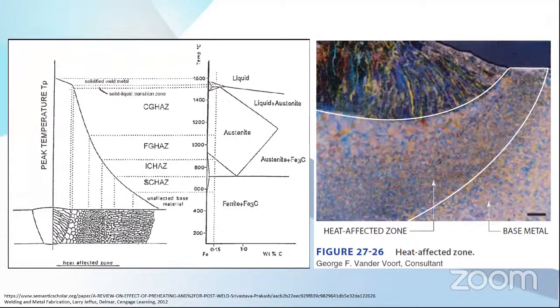This is an example of the welding zones. As you can see, the microstructure of the weldment is dendritic. This is like a chill casting, and the closest one is the unmixed zone, and then you can find grain growth and recrystallization, depending on the temperature. This is an example in a carbon steel material, and this is what you can see in the microscope. This is the weldment area where you have this dendritic microstructure, and then you have this grain growth. You have this recrystallized grain in the heat affected zone, and this is the base metal, which has the same properties as the original material.